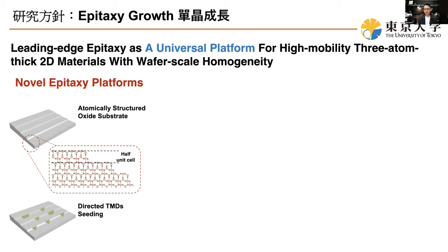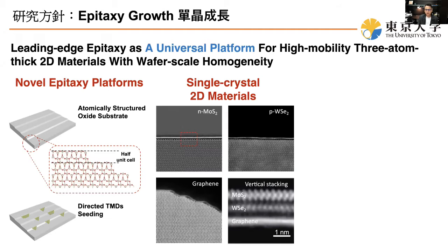So this gives us the capability to synthesize these high quality materials. And thus far, we found that with this structured platform, we are able to create a wide variety of single crystal 2D materials, ranging from N-type molybdenum disulfide, P-type tungsten diselenide, or semi-metal graphene.